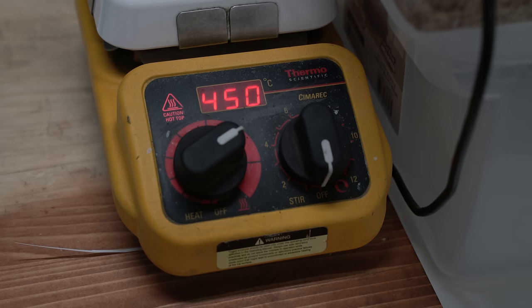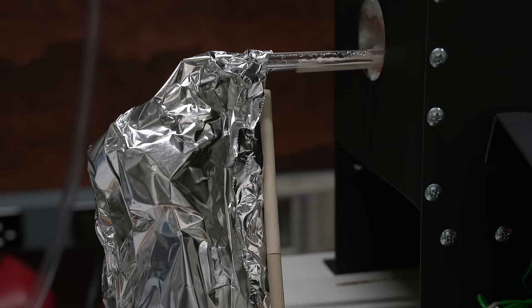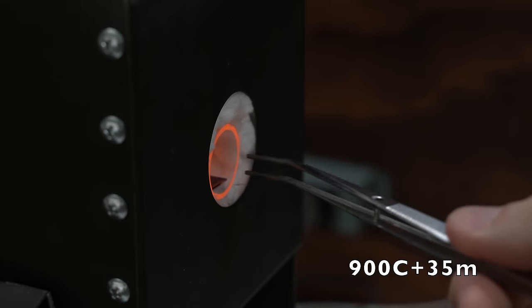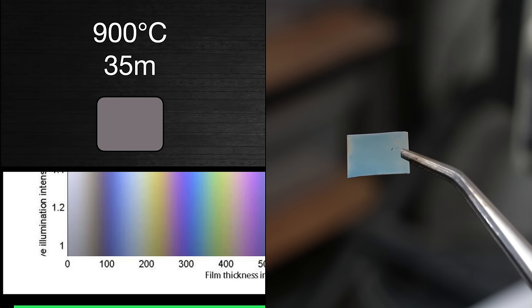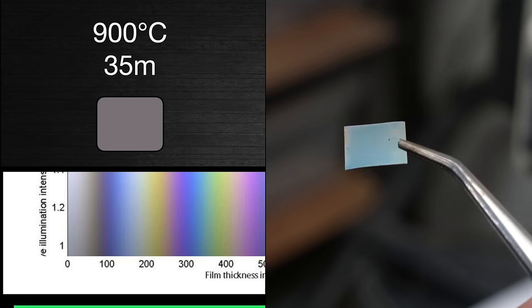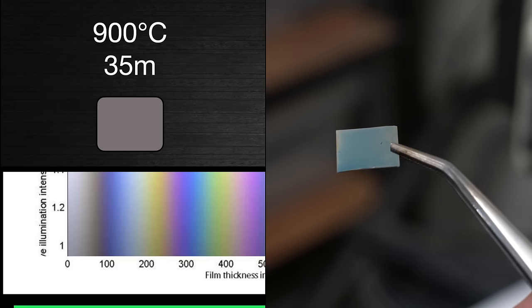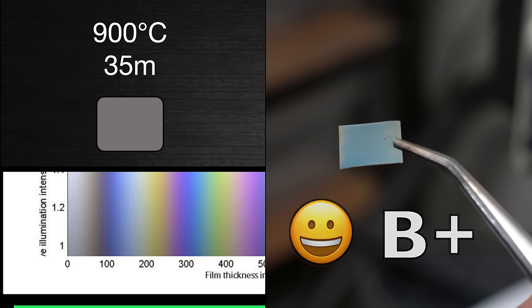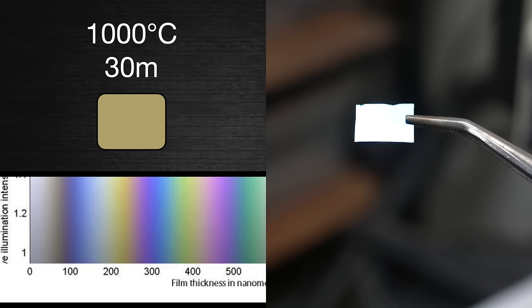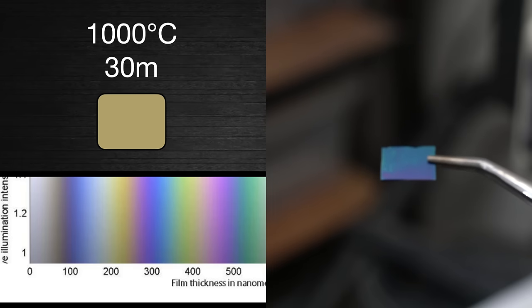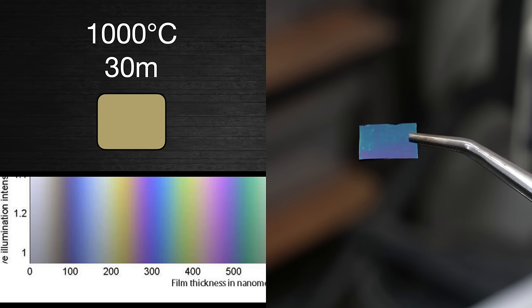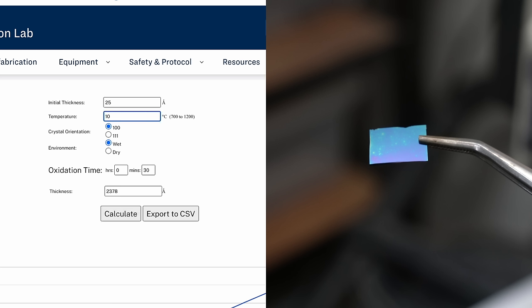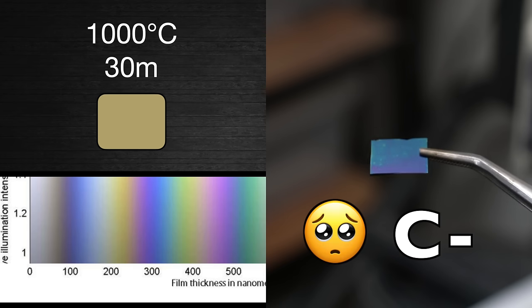I made sure this time to crank the heater and to insulate the Erlenmeyer flask with some aluminum foil. All right, first up, 900 C, 35 minutes. This one looks all right. You can see that it's brown, but it's starting to change color, so I probably overshot by 5-10 nanometers at most. I'm going to give this one a B+. Next, we have 1000 C at 30 minutes. This one is a little bit more problematic. It's supposed to be gold, about 240 nanometers, but it's clearly closer to maybe 280, 290, so we overshot a fair bit. This may seem like a big error, but it actually only corresponds to a 20 degree temperature difference. I suspect I got a bit sloppy with the thermocouple placement. This one gets a C minus.